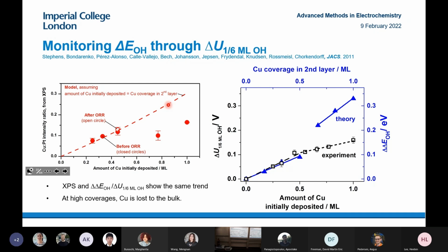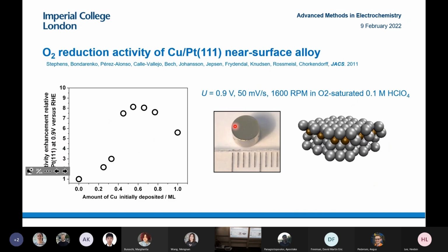And we did actually find, let's say if we annealed the single crystal in oxygen, we'd find copper would always come out of the single crystal, so it wasn't really getting lost in the single crystal. So in reality, what we find from this is that there's pretty good agreement between experiments and theory, taking into account that we're actually losing the copper, if you look at the shape of these two different figures.